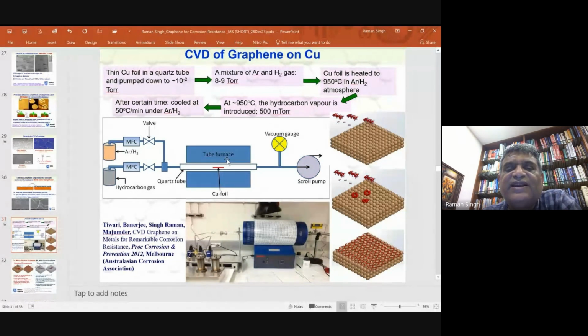And if you maintain right partial pressure, you will have graphene. If you did not maintain right partial pressure, you can have carbon nanotube, you can have diamond, you can have carbon soot. So supplying hydrocarbon at a controlled rate is essential for developing graphene. Otherwise, you will get something else. And that's how you develop graphene, and that's how we develop our own graphene in our own lab.